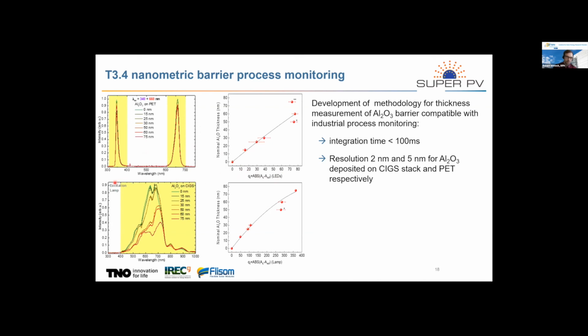The same principle can be applied here, not using LEDs, but a halogen lamp. This technique is a little bit more sensitive since you have a broader spectrum for your light source. Here you have a resolution of 2 nanometers. Here you have a resolution of 5 nanometers. But both techniques are suitable for inline monitoring, since you have integration times of less than 100 milliseconds. That allows you to monitor this thickness of this innovation also in inline manufacturing.